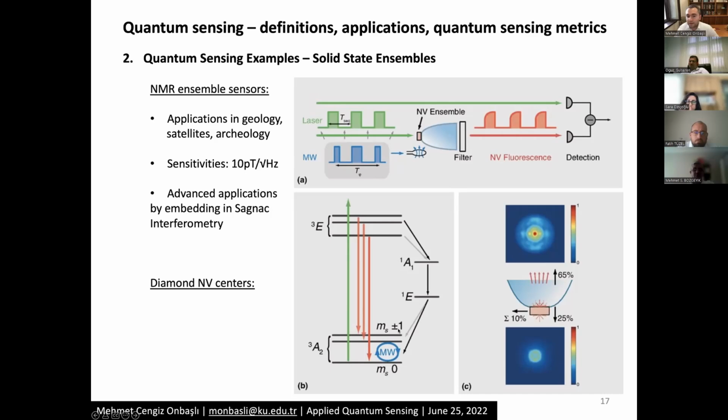Remember that these quantum numbers are going to have different footprints in the spectra if we apply a small enough microwave field externally, so that we can have slight energy differences to distinguish which transition is occurring. Since I want to understand which state I'm triggering or controlling, I want to know whether I'm transitioning from 0 to +1 or 0 to -1 or vice versa.